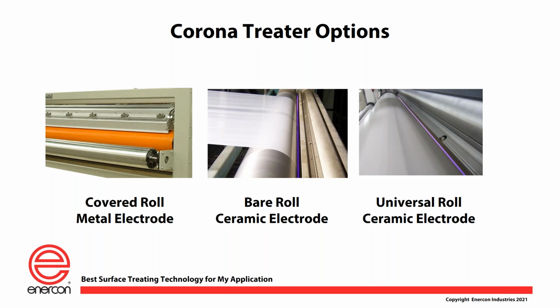If you're in film extrusion, cast film, blown film, oriented film, many times you'll gravitate over to a covered roll system of some style. The bare roll, so that would lead you to say, well, wait a minute, where does the bare roll treater come in? So again, we have a home for those. Let's say you're on an extrusion coating line and you have a secondary unwind that you're unwinding some foil, and you want to treat the foil or clean it before it goes into a laminating process. A bare roll treater would be perfect for that, because the bare aluminum roll and the ceramic electrodes, the aluminum doesn't bother that at all. It works great for that. That's just one example that comes to mind. There are others. But as you can tell from my description here, your application details, what you're currently using, and how your operations run really help determine whether it's a covered roll treater, a bare roll treater, or a universal roll treater. Next slide.